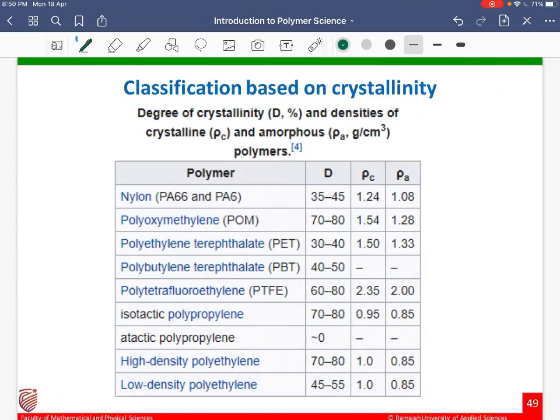Here are a few examples of polymers and their degree of crystallinity, and the density in the crystalline region and the density in the amorphous area in their structure are listed here. For nylon, degree of crystallinity is around 35 to 45 and its density in crystalline region will be 1.24 and amorphous it will be 1.08. For polyoxymethylene, degree of crystallinity 70 to 80%, so it is a crystalline polymer. Polyethylene terephthalate 30 to 40, so it will be semi-crystalline. Polybutylene terephthalate 40 to 50, so that is also semi-crystalline. Polytetrafluoroethylene, this is Teflon, 60 to 80, which comes under the crystalline polymer category.